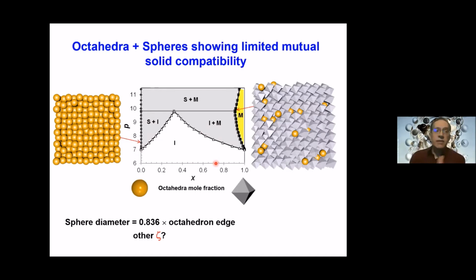But this, being an athermal system, should be very affected by entropic considerations, which are embodied in our parameter zeta, this size ratio. Now, this phase diagram was found for this particular choice, where the sphere diameter was about 0.84 the octahedron edge, which is a choice that will give you the same transition pressures from isotropic to ordered for both components. You can see that it's about 7 here, also 7 over there, that we thought would be advantageous, but clearly wasn't. So we needed to optimize this. So how can you do it?